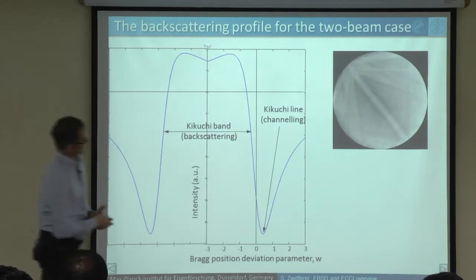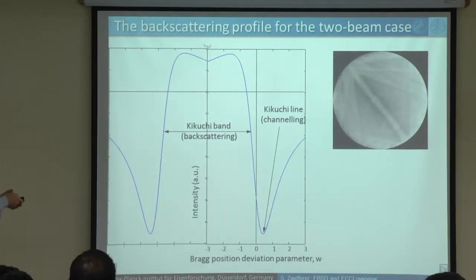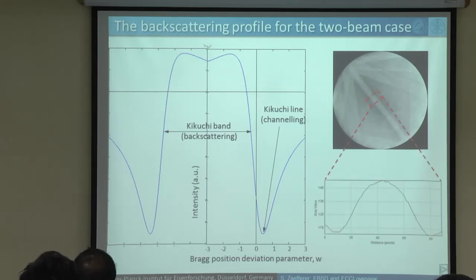Where is it? In our diffraction patterns. So we see this Kikuchi band here. It has a bright center, which corresponds to this bright area, and it has two dark sides, which correspond to these two dark sides here. No? So, and if we plot the intensity distribution across this band here, we find something which is relatively close to theory. This is a very simple theory here, which I gave you here.